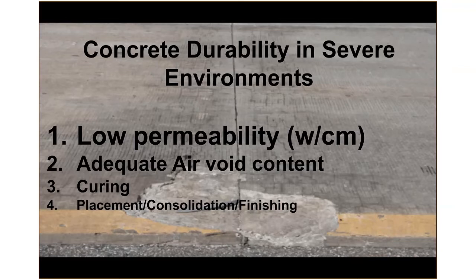Minnesota Department of Transportation has a low water cement incentive for paving, a 0.40 water cement ratio, which produces very dense concretes, which keeps water out, keeps salts out, and allows the concrete to behave better in cyclic freeze-thaw. Secondly, an adequate air void system